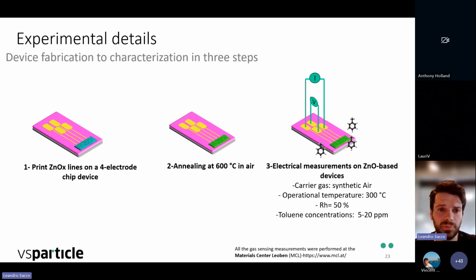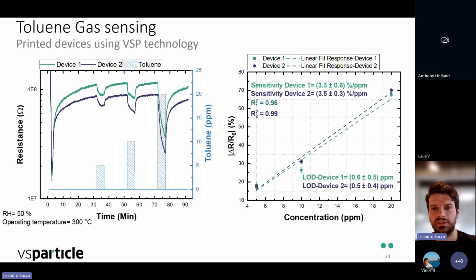And then after the annealing, we proceed with the electrical measurements of the device under the exposure of toluene. All the gas sensing measurements were carried out at the Materials Center Leoben. There you have the link if you want to see some specification of the gas sensing setup. So we were ready then to measure the response of our devices towards toluene gas molecules. On the left, you can see the resistance variation of our device. During the first 30 minutes, we let the device stabilize, and then we expose up to 5 ppm of toluene. We left the flow again of dry air, and then synthetic air, and then we expose up to 10 ppm of toluene, and we did the same protocol up to 20 ppm.